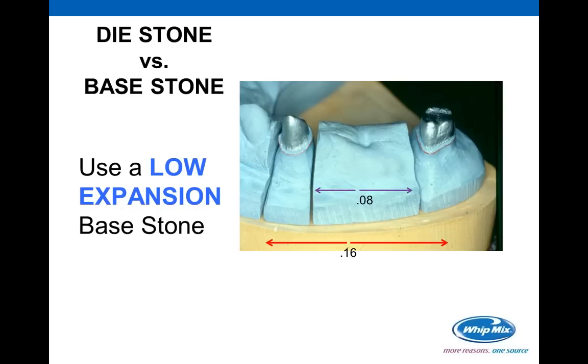If you look at the photograph here, say you use a die stone that's a 0.08, which is a low expansion stone. Let's say you leave it sit for even a couple of 3 hours. So you've got between 50 and 80% of the expansion in that time frame of the 0.08. And then you base it into a stone that, let's say it's a type 3 stone, which on average is somewhere around 0.16 expansion, almost double. And you wait for how long?